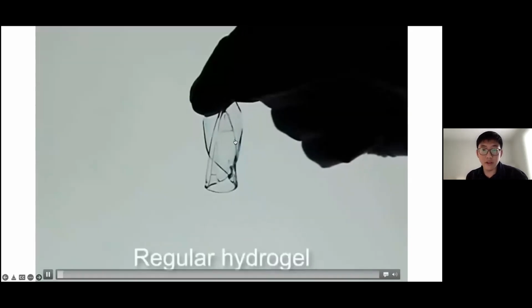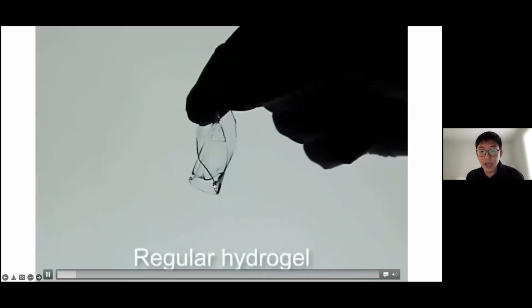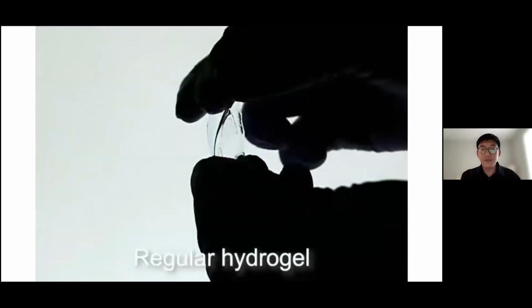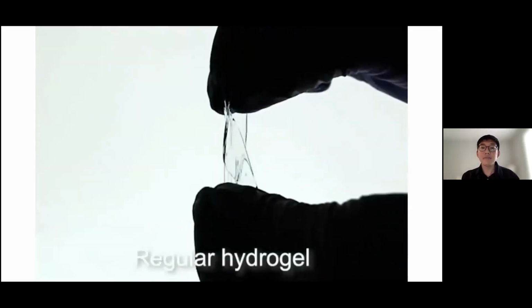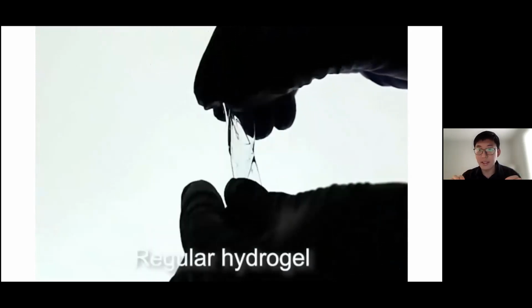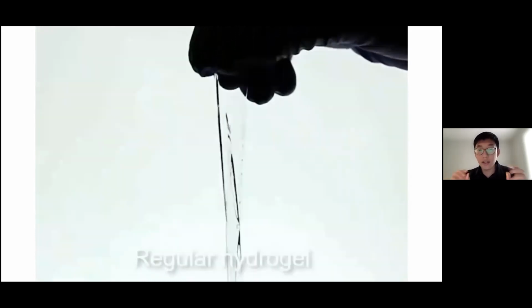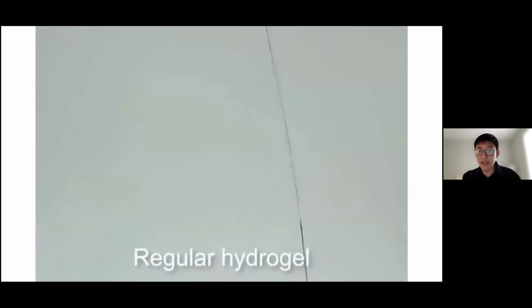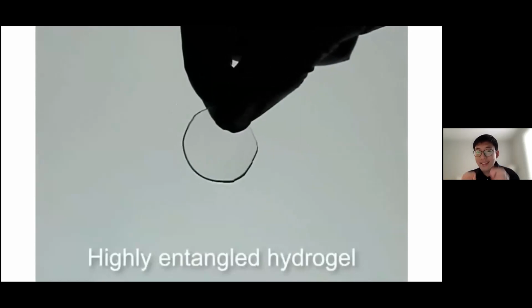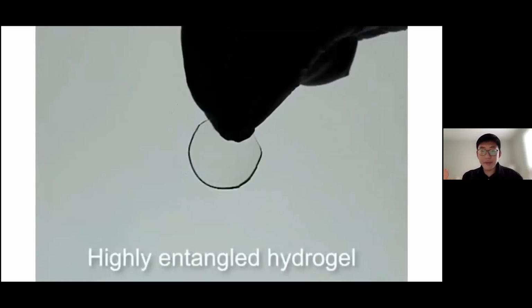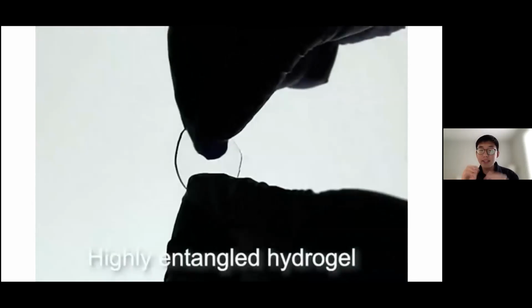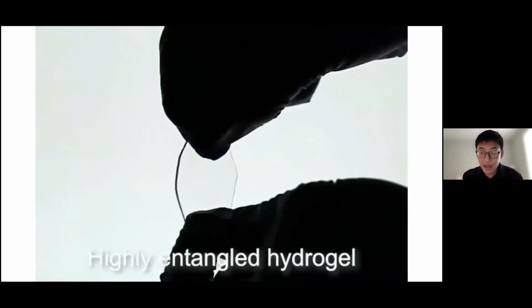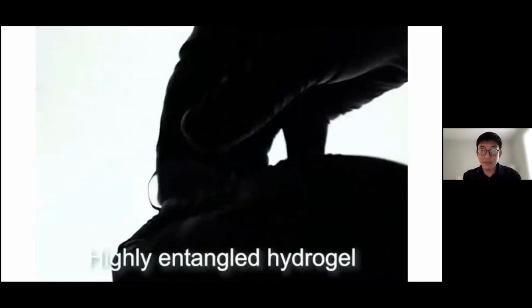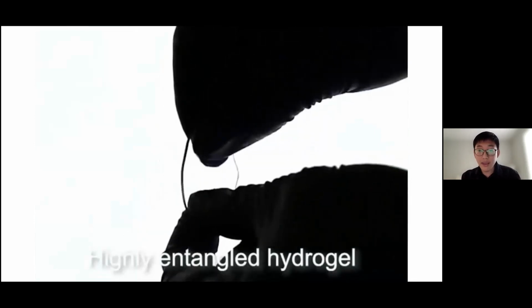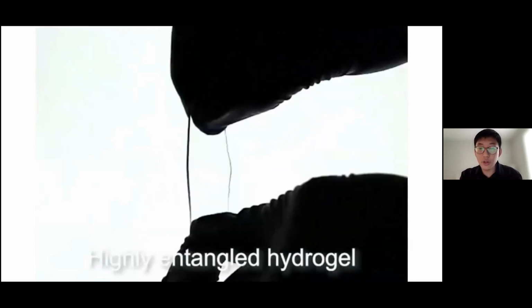Let's take a look at the view graph. So this is a regular hydrogel. That means we put enough water molecules in the precursor. That means entanglement is limited. Sparse crosslinkers and sparse entanglements. It is weak. It spreads a lot. However, if you put less water in the precursor, the polymers entangle a lot and stiffness is maintained by the entanglement. So it is very stiff compared to the regular hydrogel. Again, this material is fully swollen in water.